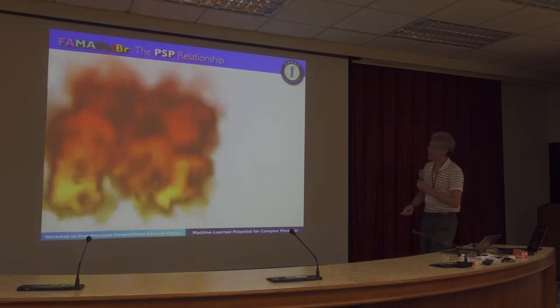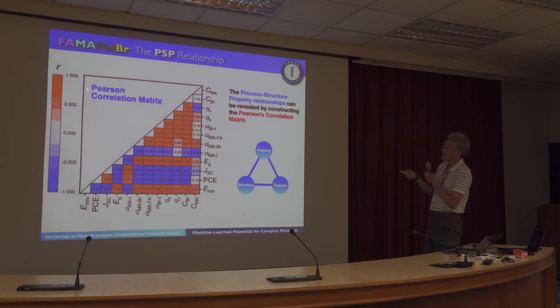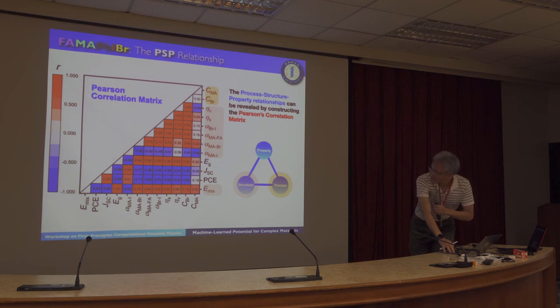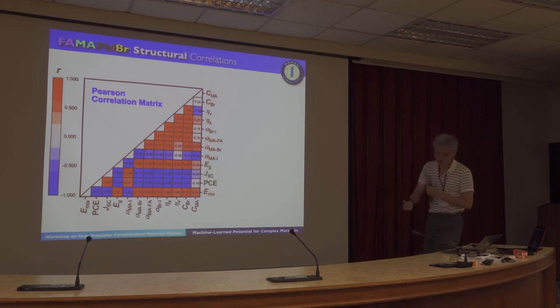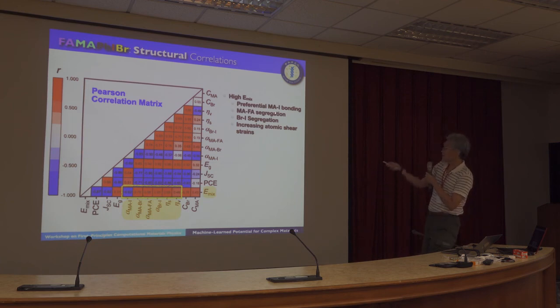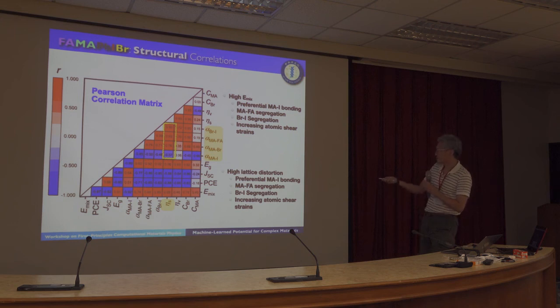And we want to see if we can consolidate everything. We want to plot everything into one single Pearson correlation matrix, so that we can reveal the process-structure-property relationships. So this is the process, this one is for structure-property, and this one is for property. So we started from structure correlations. We can find that with a high mixing energy, we got the preferential MAI bonding, segregation between MA and FA, and bromine and iodine, and increasing atomic shear strains. And then we can also find a strong lattice distortion coming with all this phase segregation and preferential bonding.